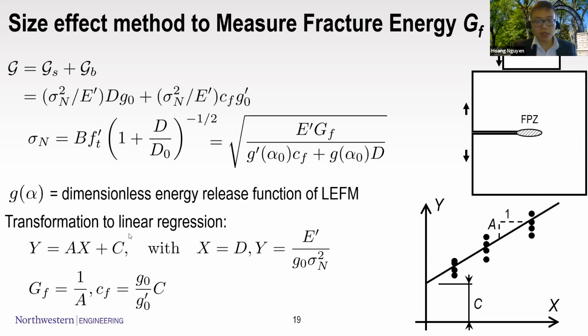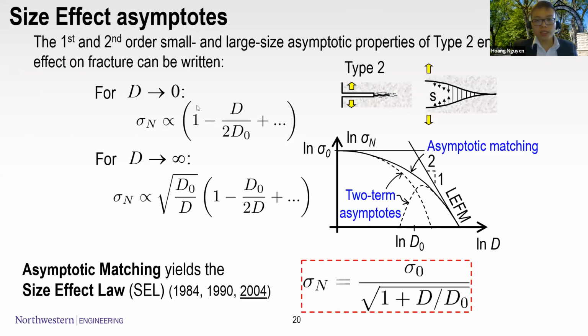And this can be turned into a linear regression curve. By fitting these, we can extract G_F and c_f, which is the characteristic length of the material. So the size effect here, you can see if we expand the size effect curve in the regime near zero dimensions, we have an asymptote when D is zero. And if you expand it with big D, then you have another asymptote for infinitely large specimens. This is the asymptotic matching that uses the size effect law, and it can be seen here.